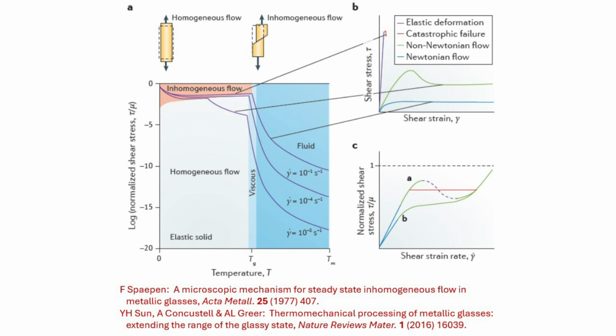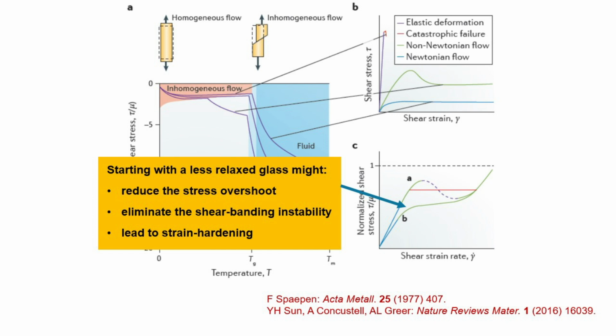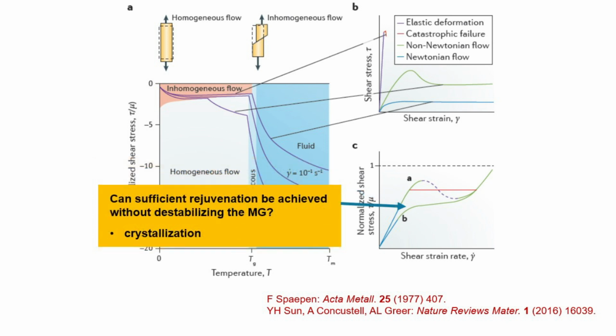Key point is, for a particular stress level, it's double valued. You have a low strain rate outside the shear band and a high strain rate inside the shear band. And we need to get rid of that if we want to avoid shear softening and the formation of shear bands. And it seemed to me one way to do it was to soften the glass to begin with. You could then imagine a smooth rise, and you'd hope to get strain hardening and to eliminate shear banding. It wasn't clear that it would be possible because it has to be a very extreme treatment of the glass, which might lead the glass to be unstable with respect to things like crystallization.